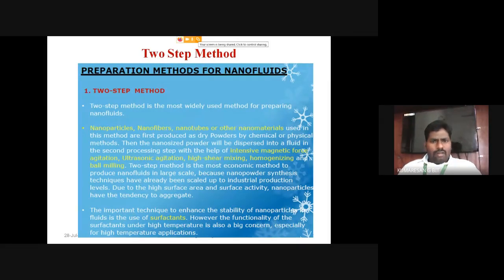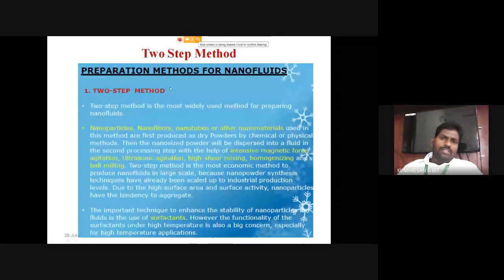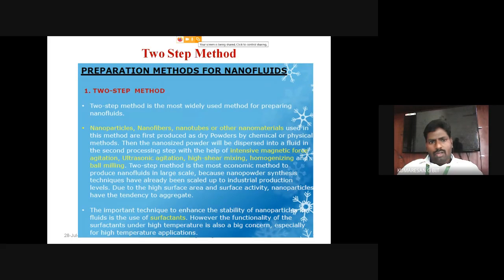And there are two methods typically used to prepare the nanofluid. The methods are a two-step method and a one-step method. The first one is the two-step method. This is the commonly used method to prepare the nanofluid. Here the nanoparticles are prepared separately. Then these nanoparticles are suspended in the base fluid like water or ethylene glycol or therminol. Okay. Then after the mixing of the nanoparticles and the base fluid, this mixture is kept in the ultrasonicator at a particular frequency to improve the stability of the fluid. Okay. Then sometimes some surfactants are also added to the fluids to improve the stability. Okay, but that depends on the density, thermal conductivity, and maybe the morphology of the nanoparticles.